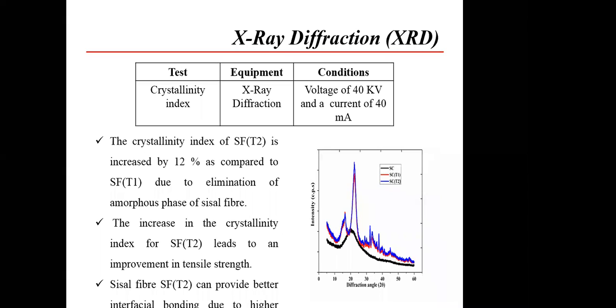X-ray diffraction (XRD) is conducted in Allahabad for measuring the crystallinity index. As we see in the diagram, untreated sisal fiber has a lower peak as compared to SF(T1) and SF(T2), that is, after sodium bicarbonate treatment and also after polylactic acid coating.